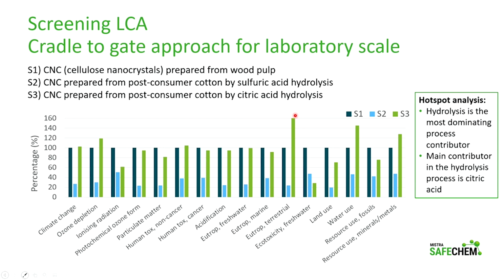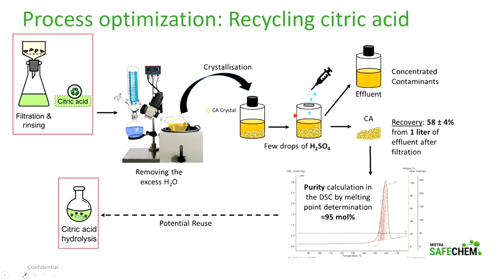And when we analyze the hotspot more closely, it is possible to see that hydrolysis is the most dominating process, and the main contributor is the citric acid itself. So we found a way to mitigate that by recycling the citric acid in the process, and we could recover almost 60% of the citric acid from the effluent, and also we got it with a high purity so that we can use it back in the process. This is the approach we have been taking, so that we can use the life cycle analysis or the toxicity screening information to improve our process and almost optimize the process for more safety and sustainability.